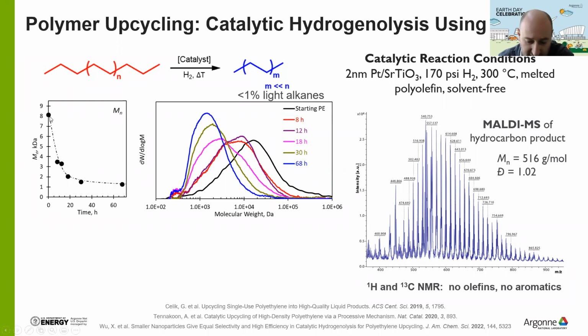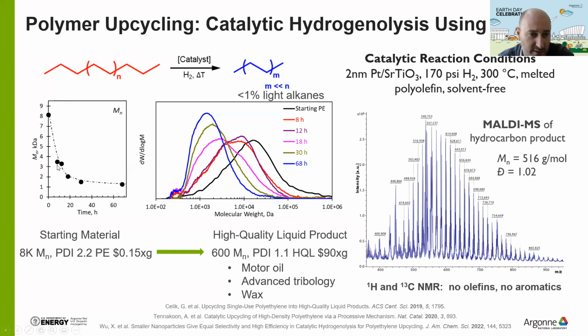And you can see that the molecular weight in this case was roughly 8,000 with a polydispersity of roughly 2.2, with a cost of roughly 0.15 per gram of polyethylene. And what we show is that we can make a new product, a liquid with a very, very narrow polydispersity. That means that all the chains in the final product have roughly the same length, with a molecular number that is roughly 600. And these are very interesting characteristics that can be used, for example, to make synthetic oil. And I will show you a couple of slides later some results of tribological properties of these liquids.